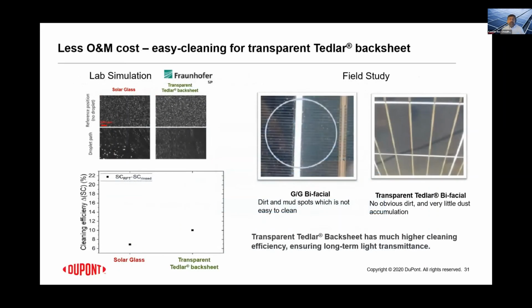I wanted to also point out what we believe is another advantage of these transparent polymer-based backsheets, in this case easier cleaning and higher resistance to the accumulation of dust. This is actually work that we conducted with Fraunhofer, and a comparison was made between solar glass in a module format versus transparent Tedlar backsheet in a module format.